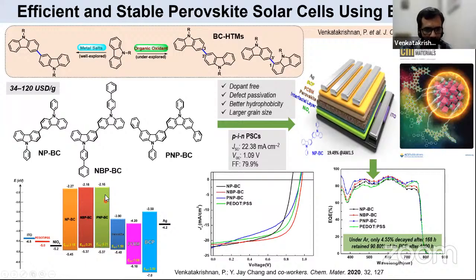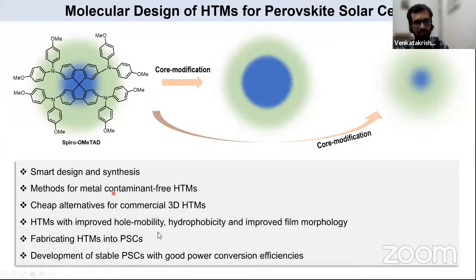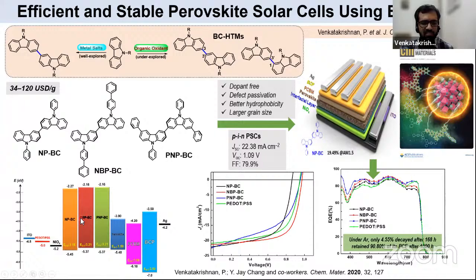Okay, look at the LUMOs, they are quite high, and thereby recombination of the electrons with the holes is hindered. So these materials are very suitable as a hole transporting material to be used in perovskite solar cells. When we use them alone, they have power conversion efficiencies of about 13%, 13.3%. But when you use this as a passivating layer between the nickel oxide hole transporting material and the perovskite absorbing layer, the power conversion efficiency of these devices shot up to about 19.49%, okay, close to 20% power conversion efficiency.